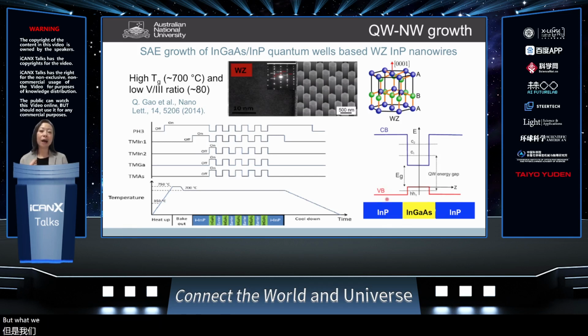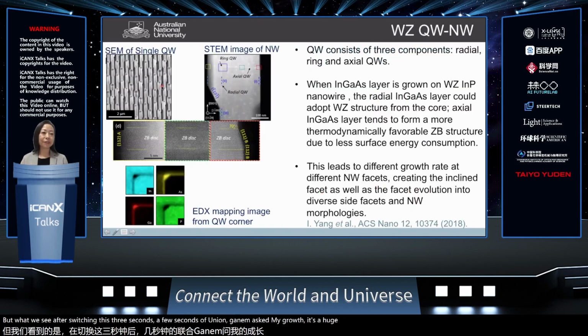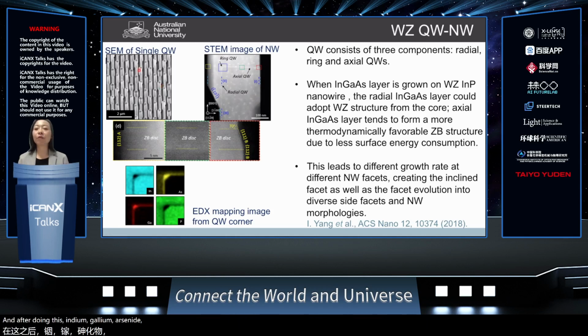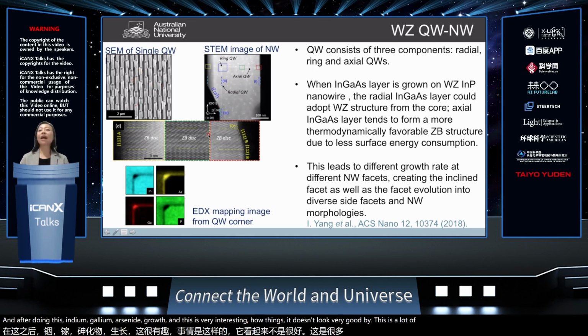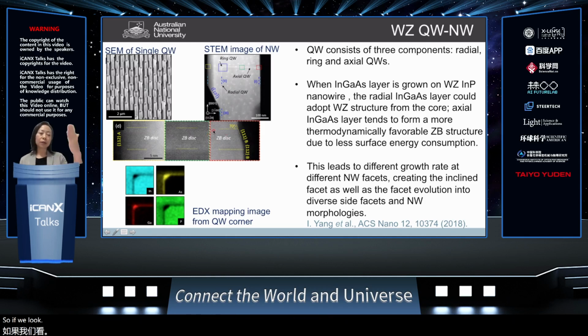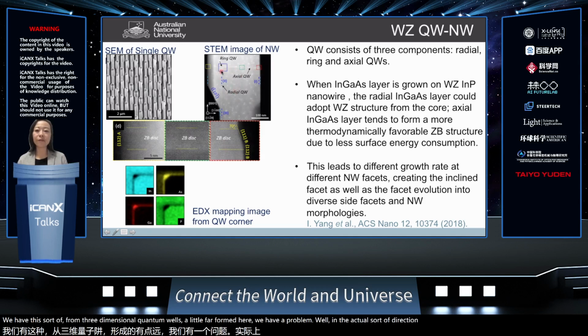But what we see after these few seconds of indium gallium arsenide growth is a huge difference in the morphology we obtained. This is a very interesting thing. It doesn't look very good, but there is a lot of interesting stuff to observe. If we look at the cross section in the TEM of this nanowire, we have a three-dimensional quantum well formed here. We have a quantum well in the axial direction, we also have the radial direction quantum well, and at the corner we call it a ring quantum well.